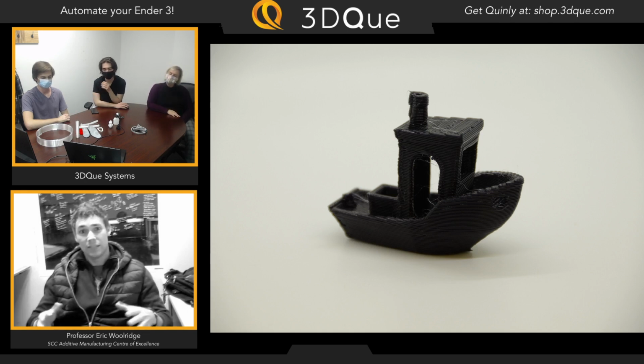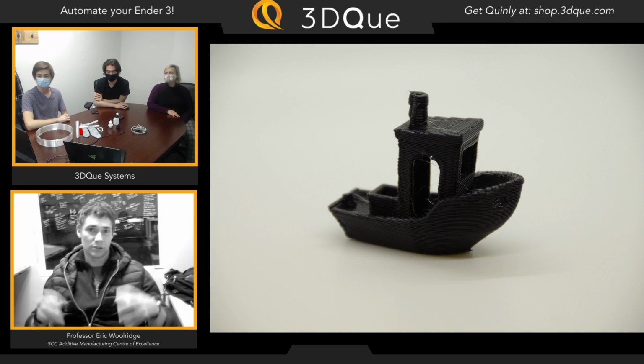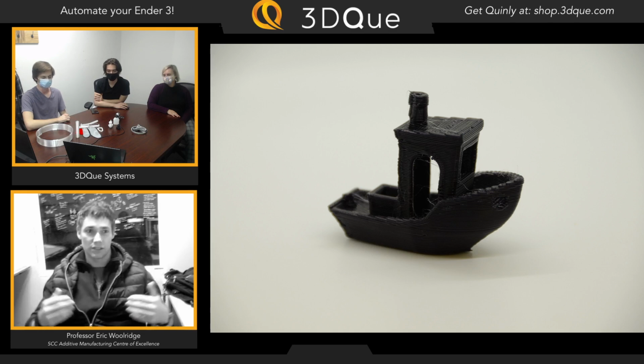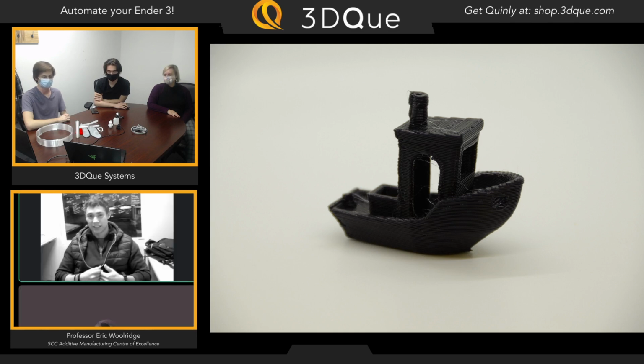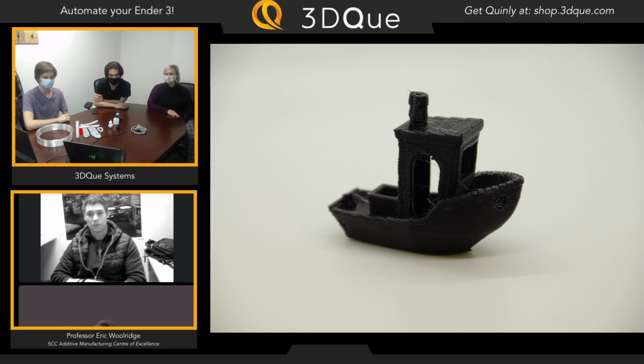You're right, the heat bed does do that. And of course, it's just shape too. If you can design your product with a better shape to accommodate that residual thermal stress, if you avoid sharp corners, that helps a tremendous amount. It's like we would see on farms. Sometimes they would run a fence this way and a fence this way, and the one on the end, the corner one, gets pulled in because you've got forces going in both directions. If you round your designs off, you'll have less residual stress. And so that's a design solution that goes with it too.